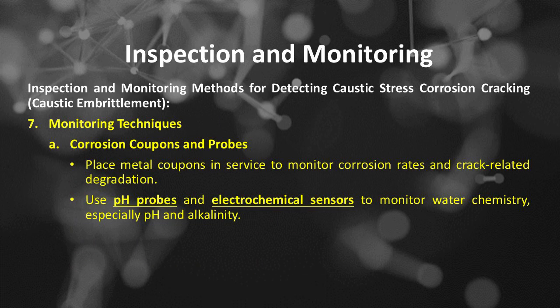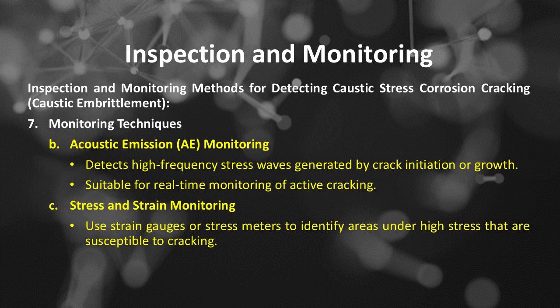Inspection and monitoring methods for detecting caustic embrittlement. Number 7 is monitoring techniques, includes, number A, corrosion coupons and probes. Place metal coupons in service to monitor corrosion rates and crack-related degradation. Use pH probes and electrochemical sensors to monitor water chemistry, especially pH and alkalinity. Monitoring techniques. Number B, acoustic emission monitoring, detects high-frequency stress waves generated by crack initiation or growth, suitable for real-time monitoring of active cracking.